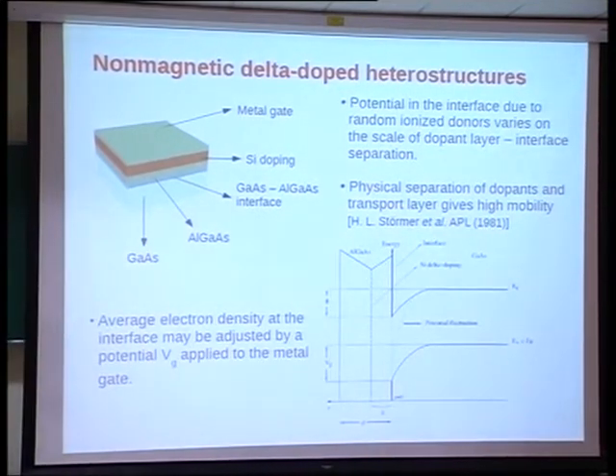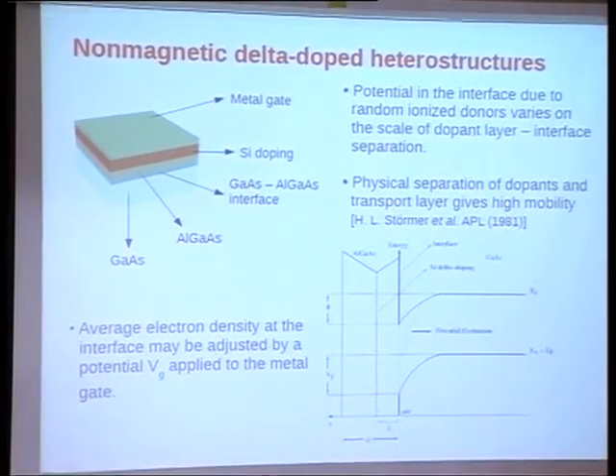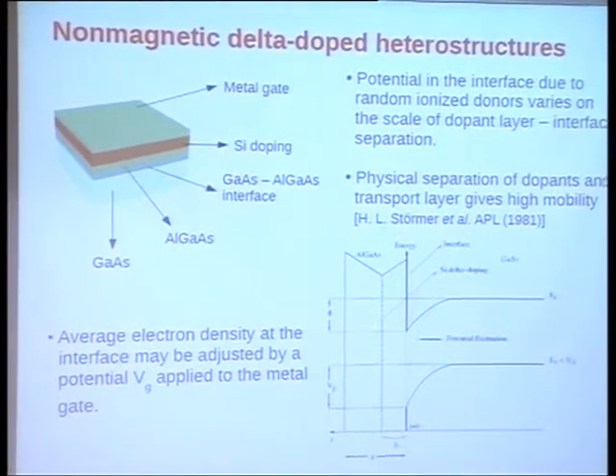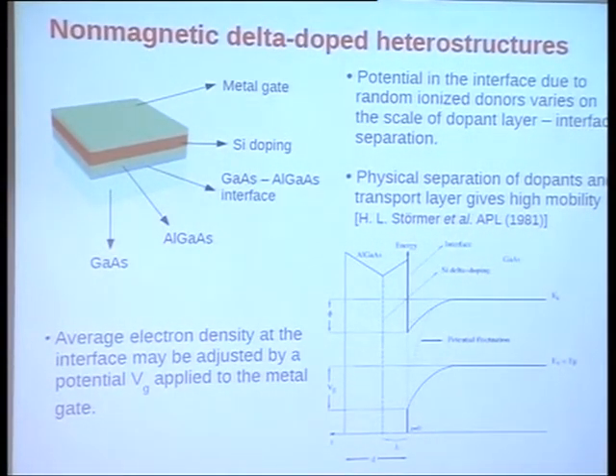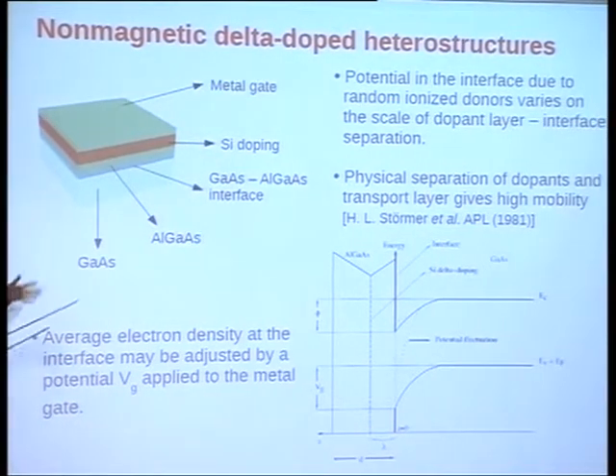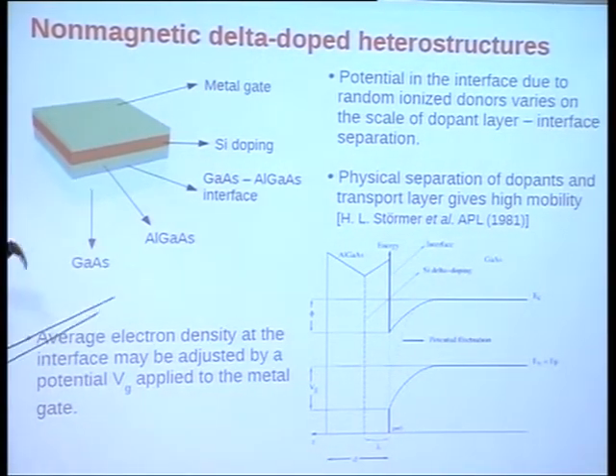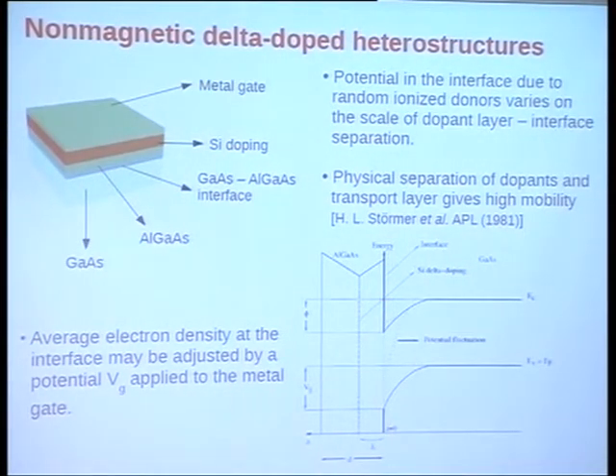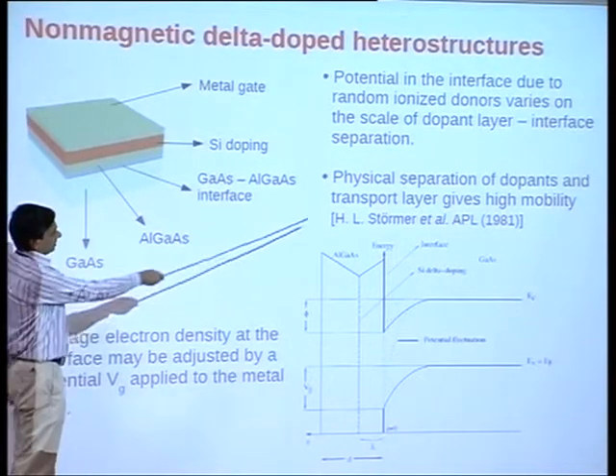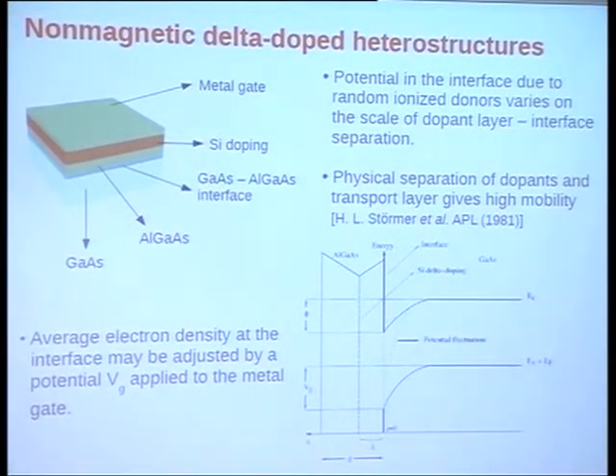And if you are studying magnetic phenomena which you think are triggered by, mediated by electrons, then this is a nice way to control the electron density. Furthermore, this can easily be made into devices where you can control the spin polarization ultimately, when you have magnetic doping here, through gate voltages. Incidentally, these heterostructures were key to the discovery of the fractional quantum Hall effect, and the main reason why these devices are created and useful is that the physical separation of the dopants and the transport layer means that scattering of carriers here is relatively lower than in bulk, and gives you very high mobilities.